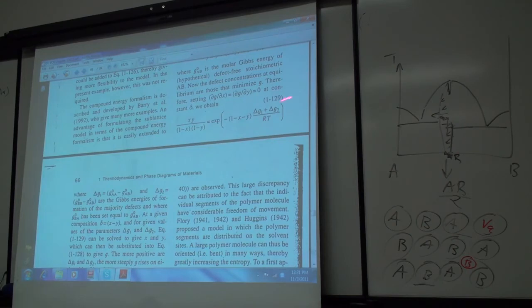Okay, because it's almost exactly the same equation, as you can see from looking at this. So just because your defect model fits doesn't mean anything really for these non-stoichiometric compounds. Any model could fit the same system. That magnesium yttrium I showed you, we know that that's the way it is because we have other evidence from the lattice parameters and the X-ray diffraction and so on, that that's the model.